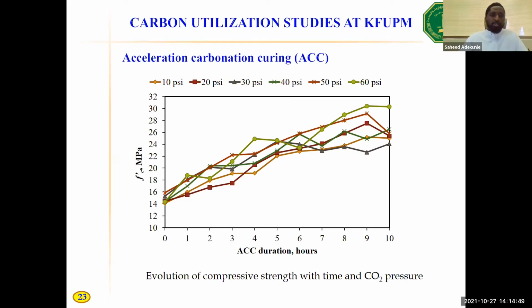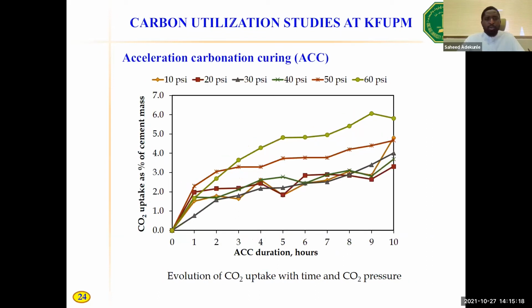And as you can see on the screen, we tried different ACC pressures, and we found that there's no significant difference between the performance of the ACC pressures. So the research that was conducted focused on the use of 20 PSI pressure in the carbonation chamber to cure our concrete element. In the same research, we achieved these CO2 uptake levels.